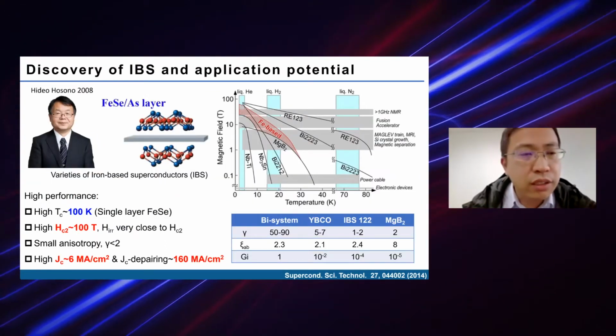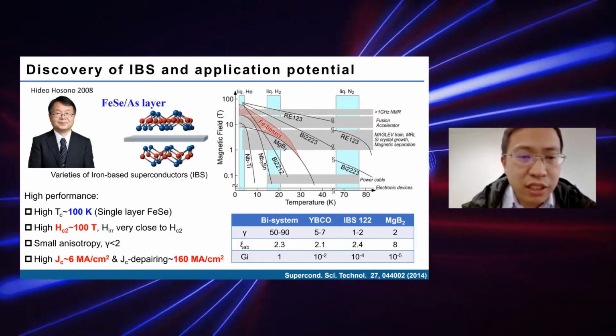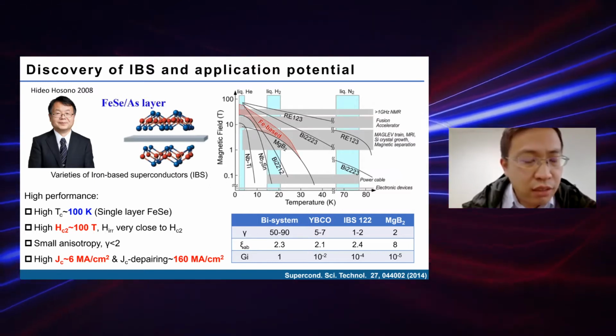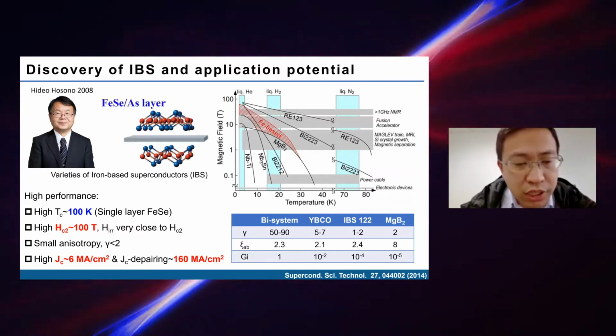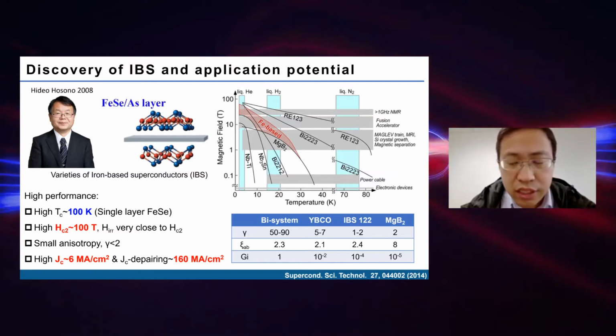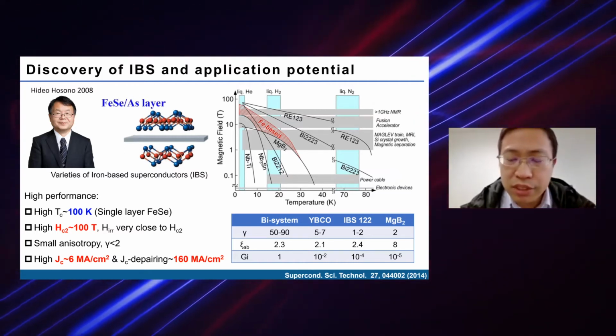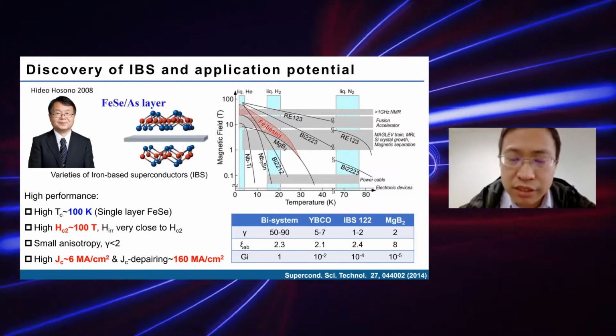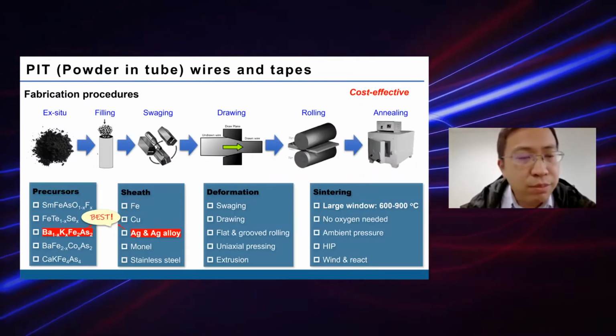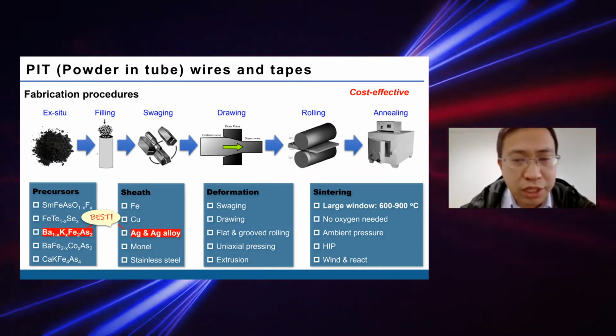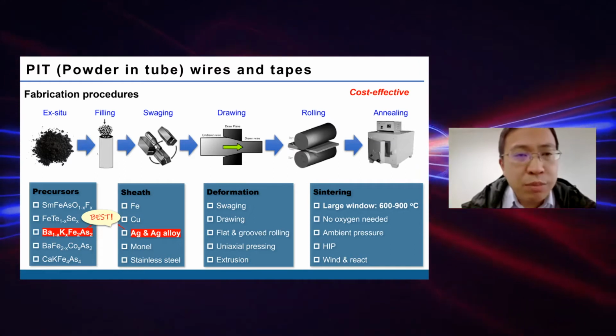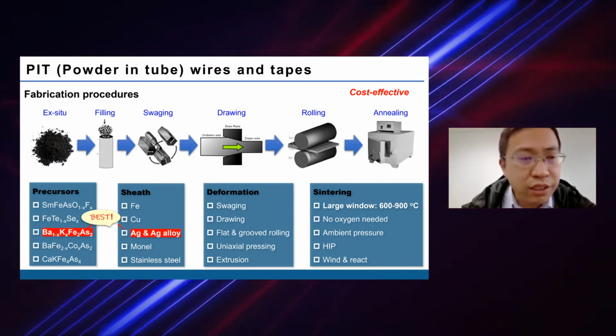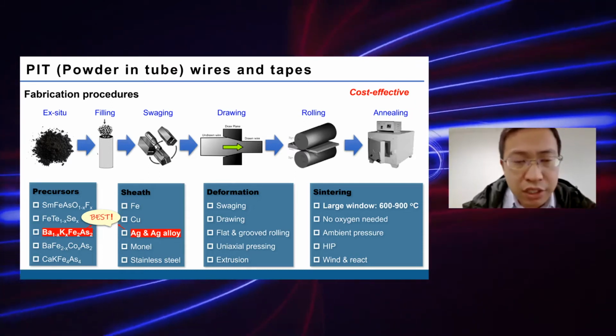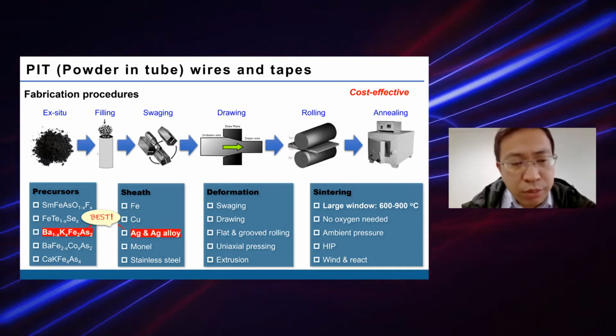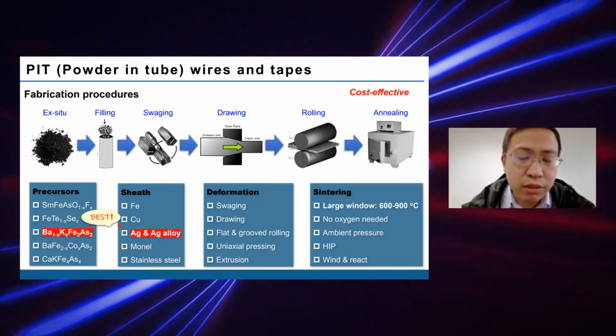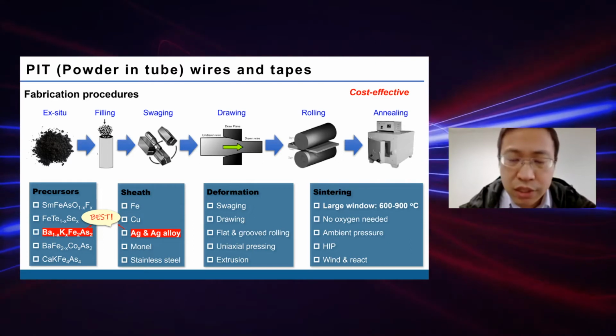In 2008, Professor Hosono discovered iron-based superconductors, which have a very high Tc, very high upper critical field, and a small anisotropy, and they have very high critical current density, making them very promising to be used below 30 Kelvin and in fields above 10 Tesla. However, iron-based superconductors are ceramics, so it's very hard to directly fabricate them into long wires. So we use a powder-in-tube method to fabricate long wires and tapes, and here are their fabrication procedures. After decades of investigation, we found that the barium potassium 122 system combined with silver or silver alloys is very good to achieve a high Jc.